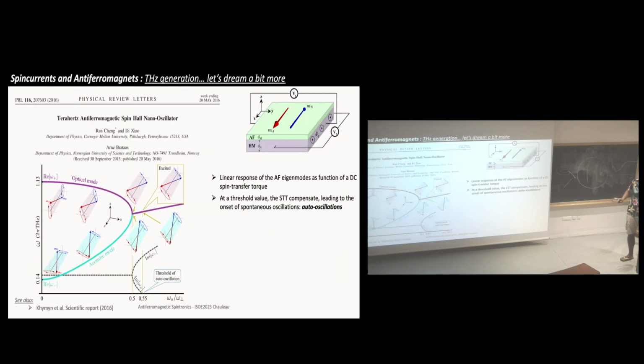I just want to give a little bit of advertisement for this one because it's a bit of dreaming, let's say. There is a prediction, because it has been demonstrated in ferromagnets and not yet in antiferromagnets, that if you apply a DC current, you can fully anti-damp the dynamics in antiferromagnets, and then you can trigger terahertz dynamics. So there would be a possibility to have a DC application of something and generate a terahertz other thing, which is very nice, because it's not so easy to generate terahertz. But in reality, it's not so easy.